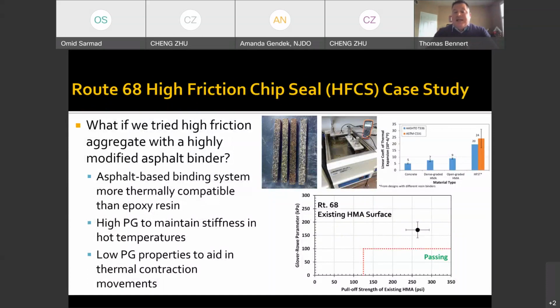So this was a section that we had identified as could be a poor performer if we use the epoxy. So what we ended up doing was we had an asphalt binder formulated by an asphalt refinery, and we used that as the bonding agent. The asphalt binder graded out to be a high stiffness, over a PG grade of 88, but still met our low temperature PG grade of -22. So that gave us a good bonding agent that should hold up in the high temperatures that would allow the aggregates to be bonded in place.